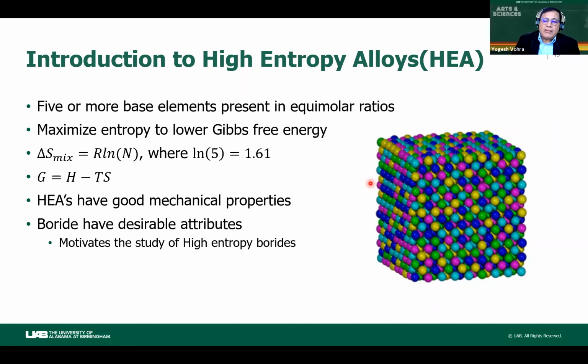And why these materials are of interest is that you can hopefully create materials which are better than the constituents, boride, carbide, oxide, and nitride, and so on. And what interests us from an application standpoint are the high temperature properties. And these materials are actually stabilized by the entropy of mixing, or configurational entropy, because the entropy of mixing is given by the gas constant multiplied by the natural log of n, where n is the number of elements. And if you put 5 here, you get 1.61 times the gas constant.